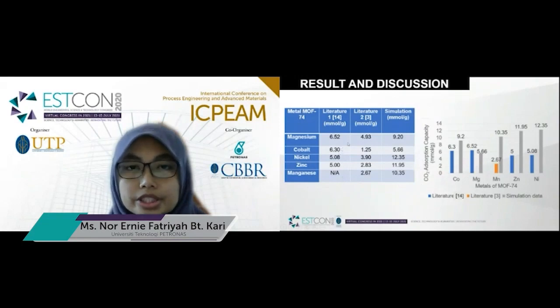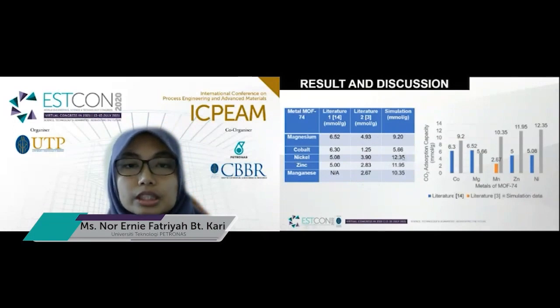In comparison with the literature, in our simulation, it is found that nickel gives the highest adsorption capacity compared with the other metal centers, and for the literature, magnesium gives the highest adsorption capacity. Even though in the literature magnesium gives the highest adsorption capacity, magnesium is reported to rupture in the presence of water, which does not comply with the adsorbent criteria, which needs to be robust in the presence of water. And nickel metal center is reported to give high robustness in water, which is 85%, compared with magnesium that is only up to 18%.